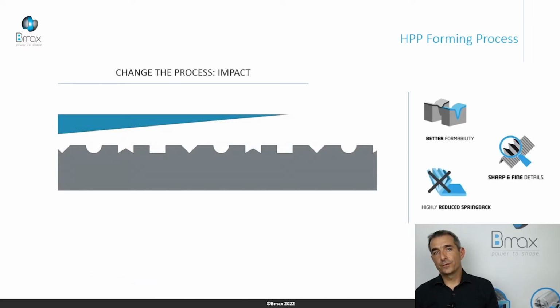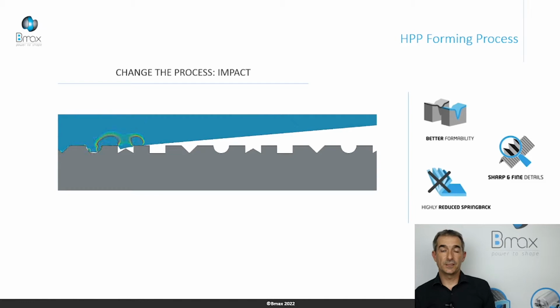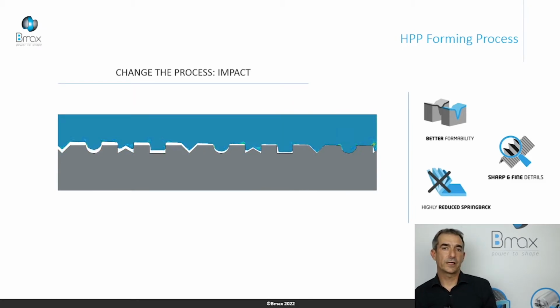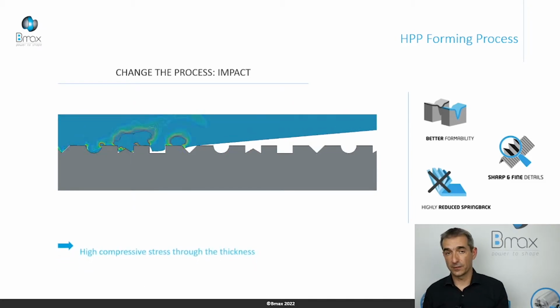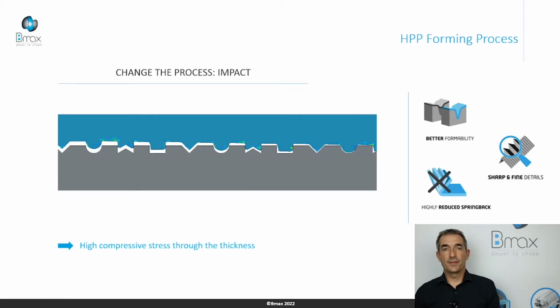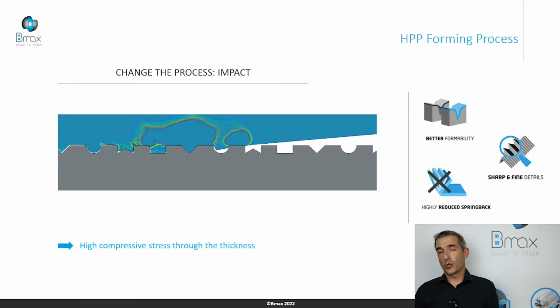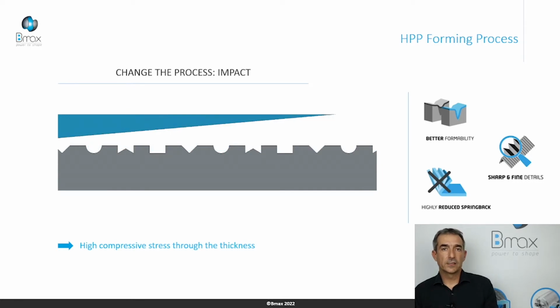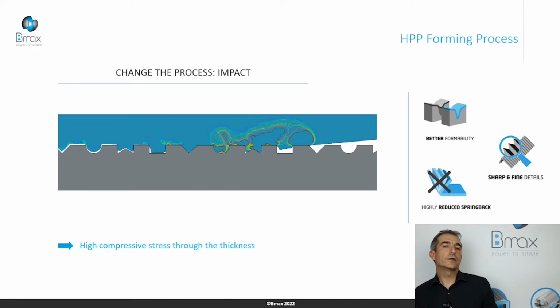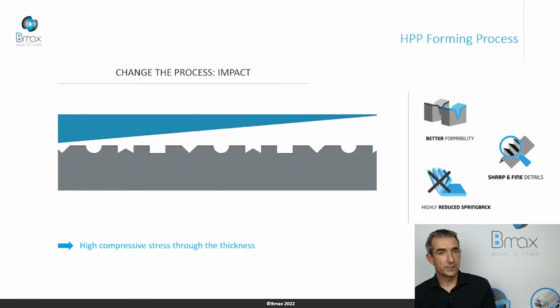Another effect of the dynamic loading is impact. Thanks to impact, we can create compressive stress in the blank, in the material, in the sample, at the interface of the impact. In this way, a compressive stress can lock any cracks, can collapse the cracks, and by this way, we can enhance formability.